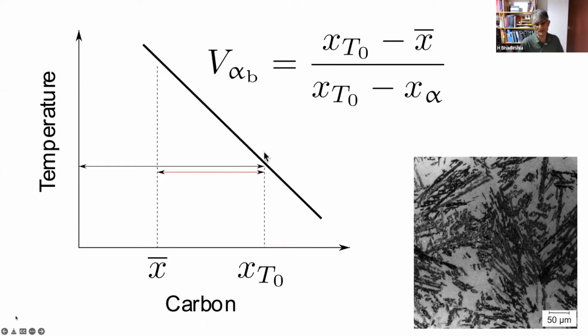Now, of course, if I lower the transformation temperature, then I will get an increase in the fraction of ferrite, but there's a limit because of the martensite start temperature. You could reduce X bar, reduce the average carbon concentration, and you would not lose strength because the strength is coming from the bainitic ferrite. But you would consume the blocks of austenite. Or the T0 curve can be shifted to the right by appropriate alloying with substitutional solutes.